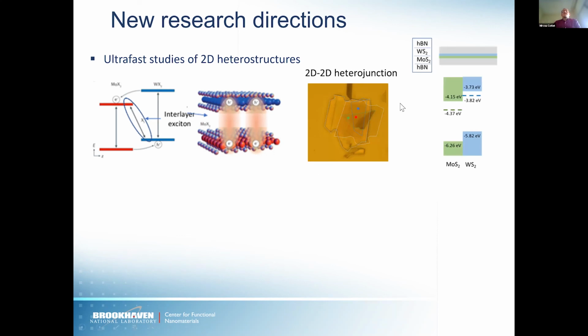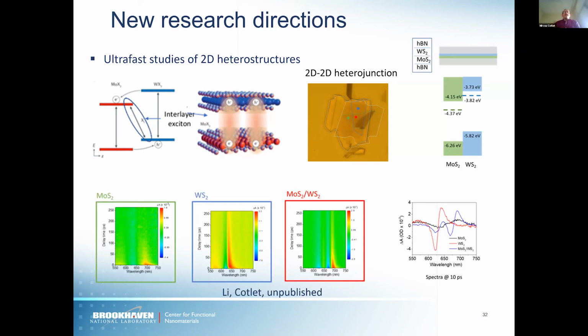A structure is shown here, which has been built by a colleague of mine with molybdenum disulfide and tungsten disulfide kept between hexagonal boron nitride, and the band gap alignment here promotes the formation of strong interactions, and the ability to do transient absorption studies, where you can measure donor, acceptor, and donor together with acceptor to see a lot of dynamics. These are unpublished results, so I don't want to comment too much on them.